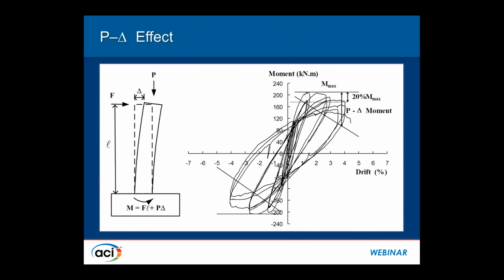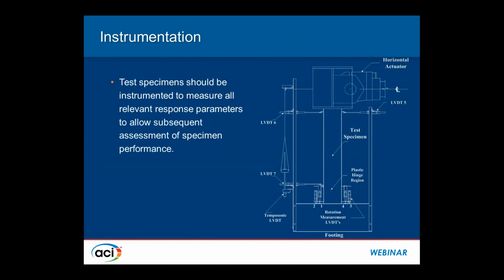If you do ignore this effect, and if you plot only F, then there will be a higher rate of strength degradation, which may or may not be misleading, because some of the moment will be used up by P delta. In other words, some of the capacity of this column is resisting P delta moment, the rest is resisting FL, and that has to be identified.